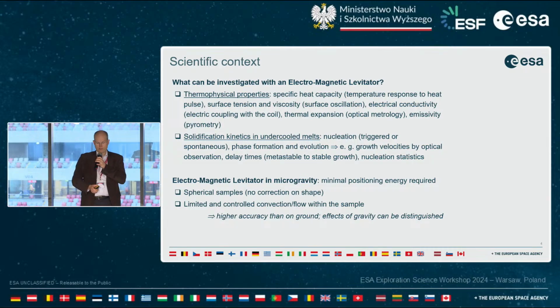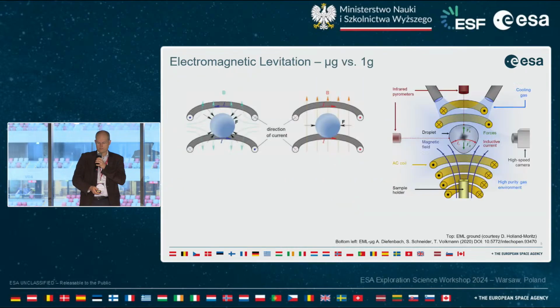We do this in microgravity because you need minimal positioning energy. You have a spherical sample, which makes some of the measurements that I just described possible, and we limit fluid flow, so convective flow, or we are able to control it in a precise way. So at the end we get results that provide us with higher accuracy, and we can distinguish the effect of gravity on these processes.